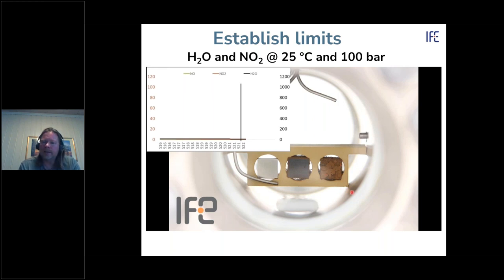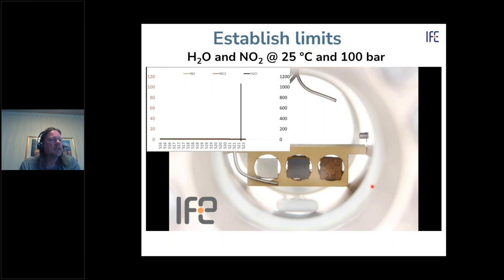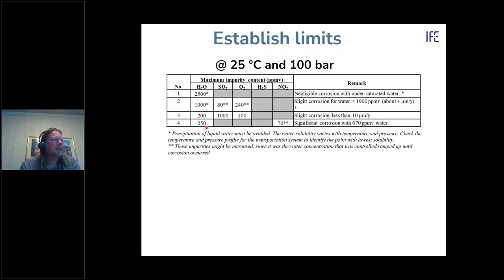We needed to understand the reactions. The experiments clearly showed that nitrogen monoxide and nitrogen dioxide fluctuate counter to each other — they are linked by reaction with oxygen. This means if you have a little NO2 and a lot of oxygen, you will never eliminate the NO2 unless it drops out as nitric acid. We also confirmed that H2S and NO2 react — an unharmful reaction unless water limits are exceeded and an aqueous phase forms.